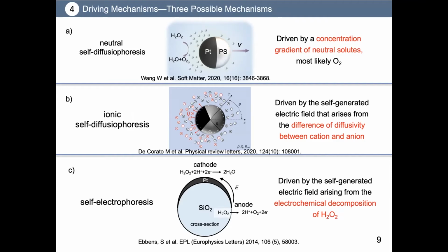The first is neutral self-diffusiophoresis, where micromotors are driven by a concentration gradient of neutral solutes, most likely oxygen. And the second is ionic self-diffusiophoresis arising from charged intermediates such as protons or radicals, where motors are driven by the self-generated electric field that arises from the difference in diffusivity between cation and anion. And the third is self-electrophoresis arising from the electrochemical decomposition of hydrogen peroxide that happens on the surface of the platinum cap.